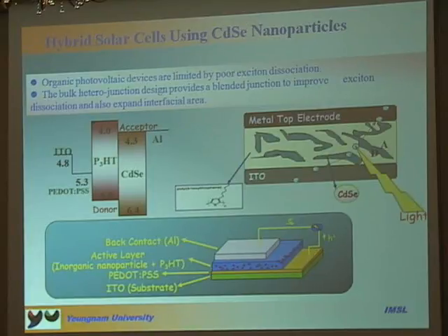Let me talk about the hybrid solar cell using CdSe nanoparticles. You know, organic photovoltaic devices are limited by poor exciton dissociation, but with the bulk heterojunction design, we can improve exciton dissociation and also expand the interfacial area. In our research, we use P3HT polymer as the donor material and cadmium selenide nanoparticles as the acceptor material. Here in the figure you can see this structure in our experiment.